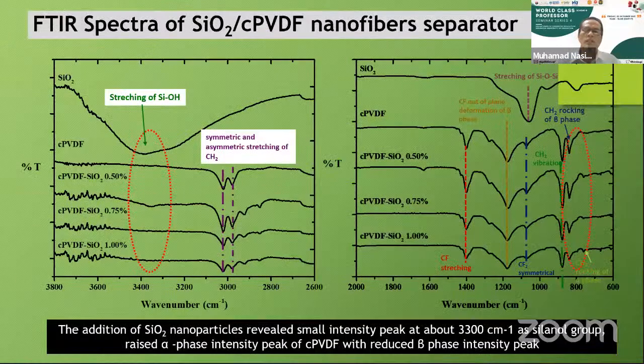We confirm the functional groups of the composite. We can observe them by infrared spectroscopy. We can see here the silanol group of the silica. And we can also see the effect of silica on the crystal structure or crystal phase of the PVDF. You can see here the beta phase content decreased with increasing silica content.